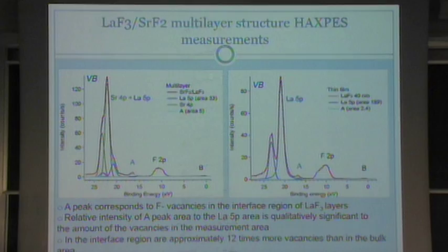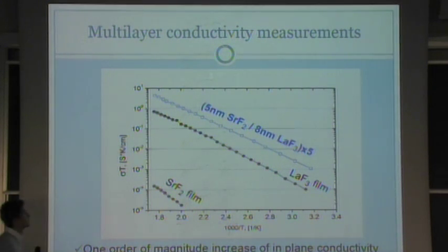On the next slide, we tried to analyze the quantity of the vacancies in the interface through the area of these peaks. The A peak is related to fluorine vacancies, and the lanthanum 5p blue peaks are related to the overall quantity of lanthanum. Through this relation, we were able to understand that we've got about 12 times more vacancies in the interface, which is significant, and it was actually proved with the conductivity results presented here on the slide, which show one order of magnitude increase of conductivity in the layers of the same structure.